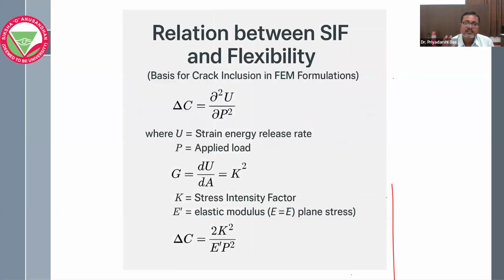So for this, we need the crack analysis. Here, the relationship between the stress intensity factor and flexibility that has been formulated here is: delta C is the local compliance. So the local compliance is nothing but the flexibility. U is the strain energy release rate. P is the applied load. For this, we can find the local flexibility as 2K squared by E P squared.